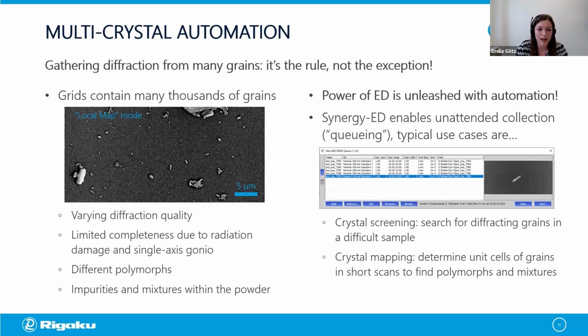Which basically means finding out what compounds you have in your powder in the first place. And you can get a good idea of this by just taking relatively small wedge, let's say over 40 degrees of total collection angle, and by this unambiguously identify the unit cells and assign each grain to a certain compound or polymorph. So you'll know what is actually inside your powder, even if it's a mixture.